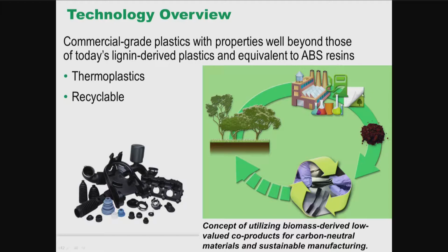And then all those biorefineries are producing co-product lignin, which is almost 15 to 35% of the dry mass fraction of biomass, and those are currently being burned. And then this can be utilized in this way to make some bioplastic. Now, here in this cartoon, I'm showing that these bioplastics can be induced to biodegradability, although we are not doing that work at this moment. Some work is going on in different sectors, and we can talk about that later on.